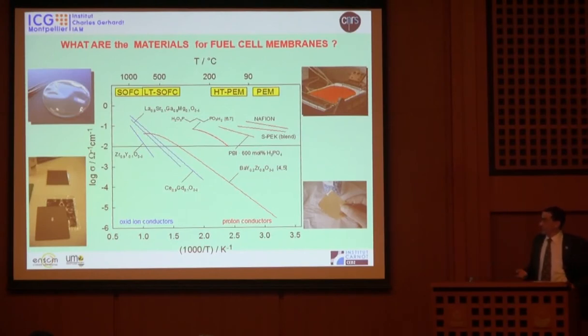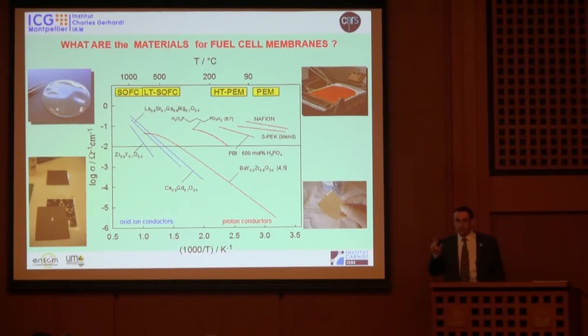And regarding the material, I'm going to focus today on the polymers and also on the membranes you are producing from these polymers. You can see that the conductivity is very important versus the temperature. So I put the temperature here on the top. For polymer electrolyte membranes, I will come back to Nafion or Flemion and sulfonated PEEK, PEK. Or at medium temperature, you can have other systems with phosphoric acid, which is very interesting. Phosphorus is very important because you can have some compatibility with electrodes. You can have flame retardancy, anti-corrosion, and acidity. And I will come back also during my presentation to making some new phosphoric acid polymers.